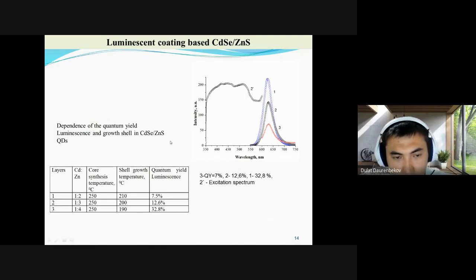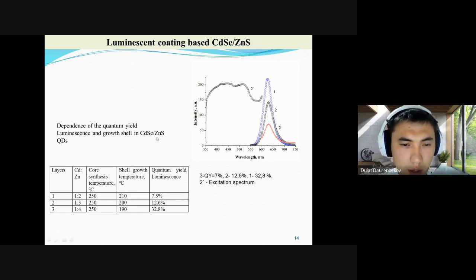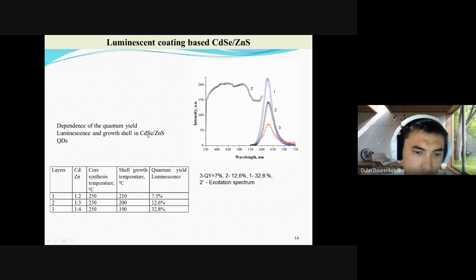Okay, for this case, we studied the core shell system. We understand that if we use only quantum dots, cadmium selenide for example, it's not enough because their efficiency is very low. As I said, surface states have a bigger influence for quantum dots. That's why there are a lot of surface defects like vacancies and other defects, a lot of dangling bonds. They're like traps for electrons and holes. That's why we should create a core shell system. A core shell system passivates the surface states.